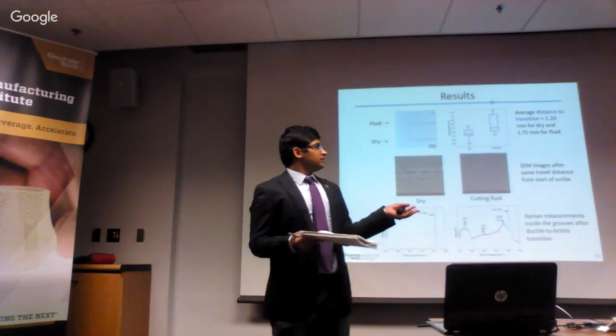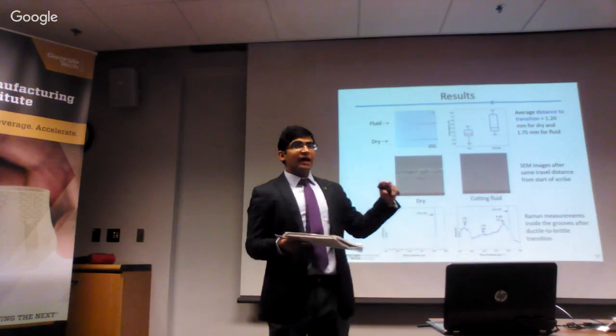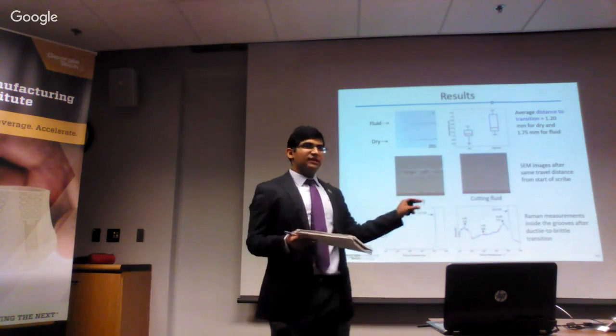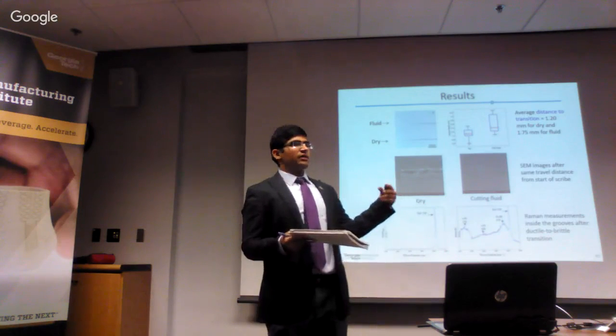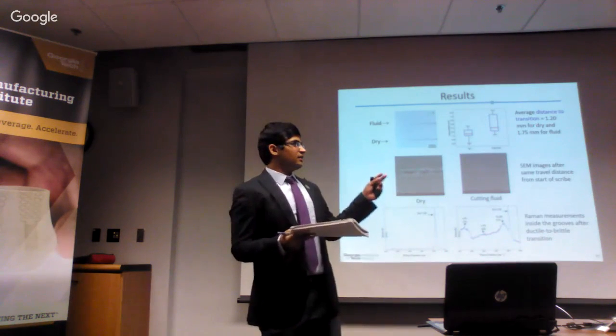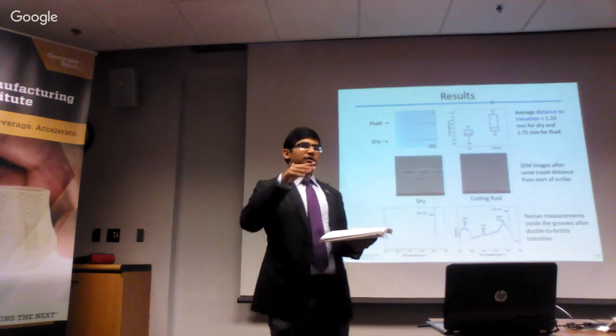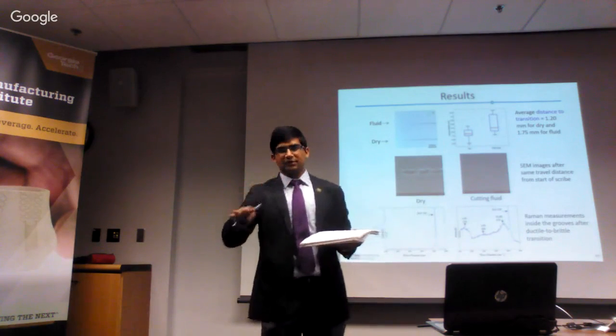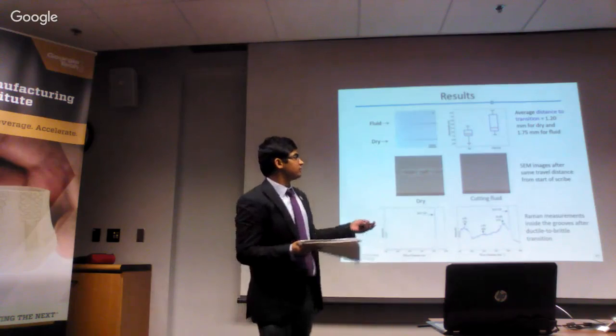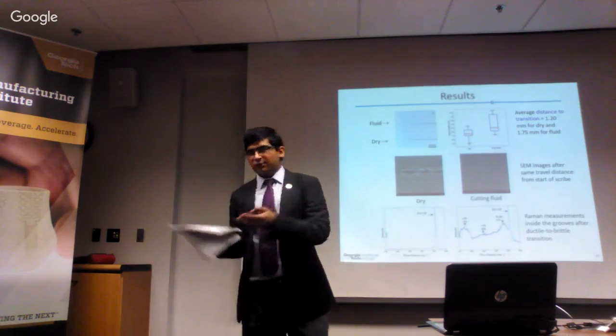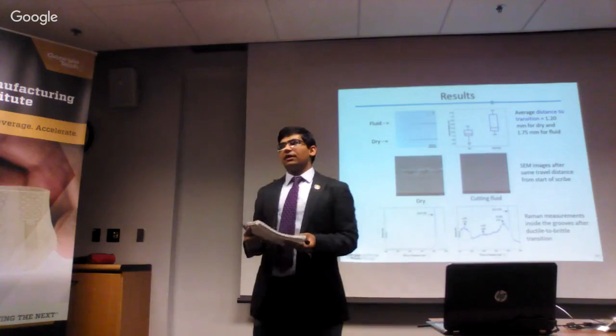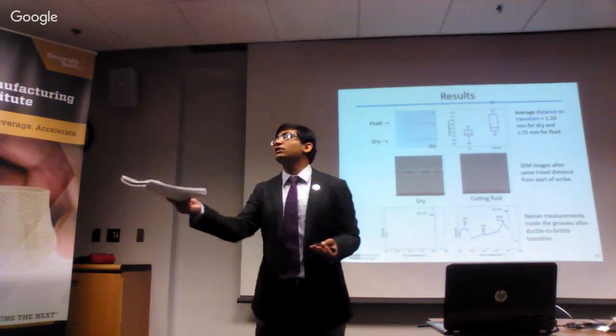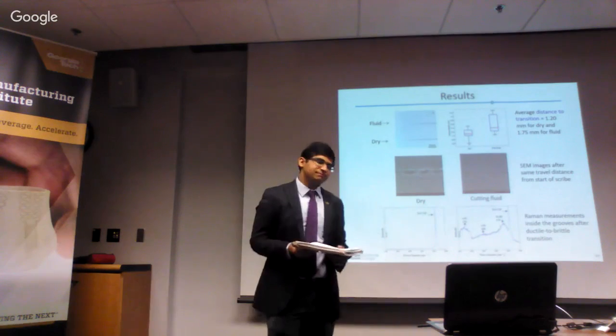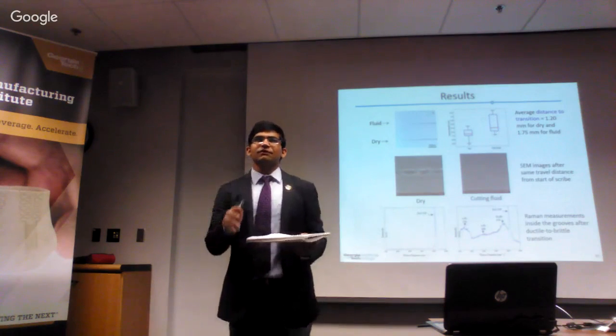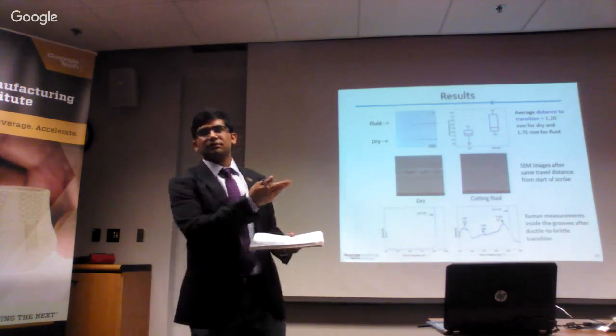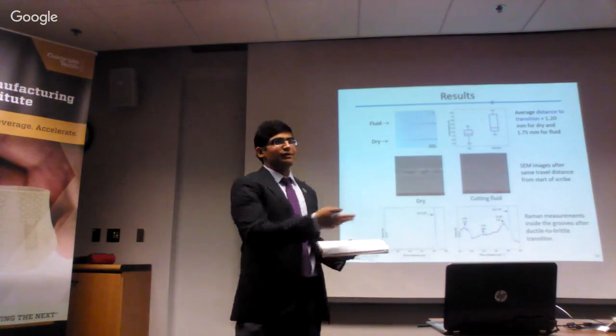differently. So because of the ionic liquid in contact with the silicon, which is the electronic material, we are providing this hypothesis that here also, because of the ionic liquid, it causes some surface charge, which causes the dislocations to move and make it softer. But you're right that we cannot. There might be the effect because the load is there. You have not verified the dislocation. I'm basing this hypothesis on the previous work of Westwood and Yost and Williams.